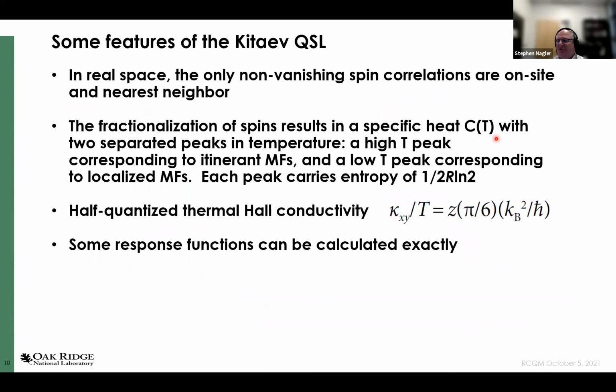So now here are some other features of this special quantum spin liquid. First of all, if I look at spin-spin correlations, the only ones that are non-vanishing are either the spin's correlation with itself or correlations with the nearest neighbor. Okay. Second fact, each spin can be considered as fractionalized into 3 fluxes and a mobile fermion. This results in a specific heat. If you had this system exactly, the magnetic specific heat would have 2 peaks as a function of temperature. The high temperature peak corresponds to the itinerant Majorana fermions and a low temperature peak corresponds to the localized Majorana fermions, each one of which carries an entropy of a half R ln 2.